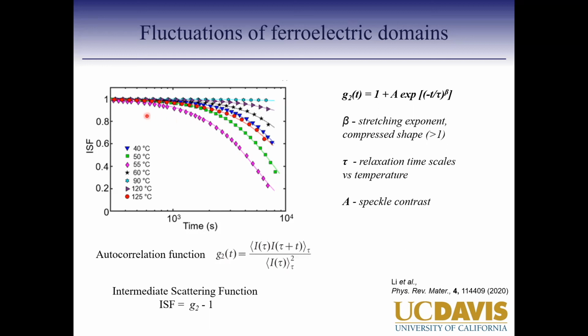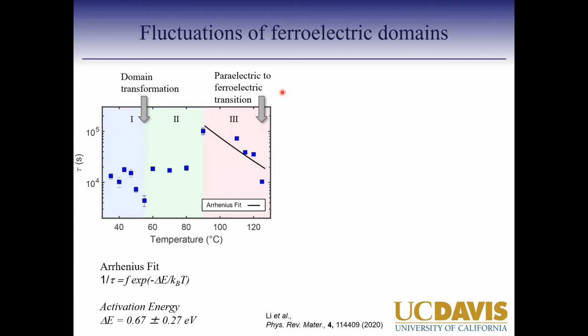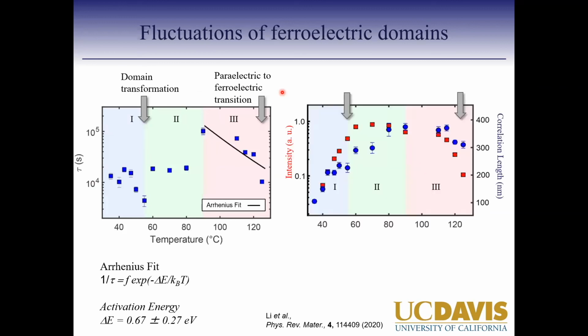We have done some other samples where we measured at temperatures of 125 C, where we also saw flat lines where nothing changes. So from there I can say that these are really changes in the samples, and the beamline is stable at these temperatures. As to how exactly the timescales are so slow, and what sort of mechanism is behind it, that's really a good question, and to be honest, I don't have a very good answer for it.